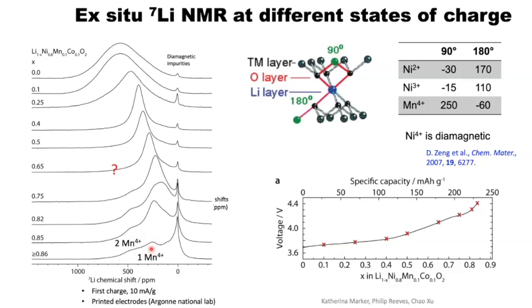We can assign this particular peak here to lithium surrounded by 1 manganese, and this one to lithium surrounded by 2 manganese, because each lithium that sees 1 manganese in a 90-degree interaction, this lithium-oxygen-manganese 90-degree interaction, gives you about a 250 ppm shift. So that's all explainable. At this point, all the nickel is 4+, so it's diamagnetic. The question is, what's going on there?